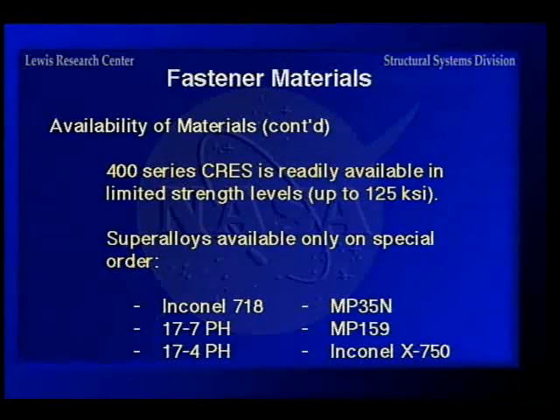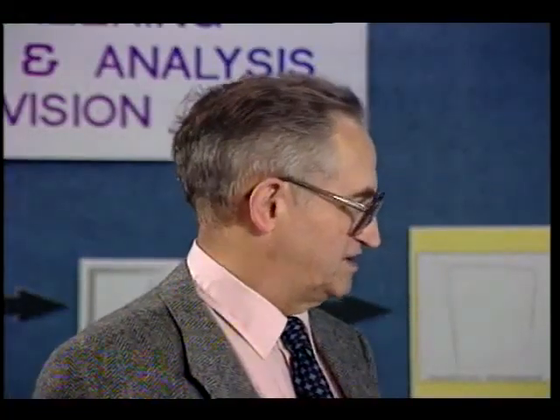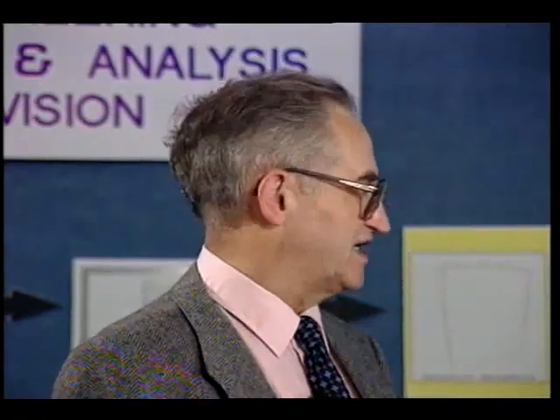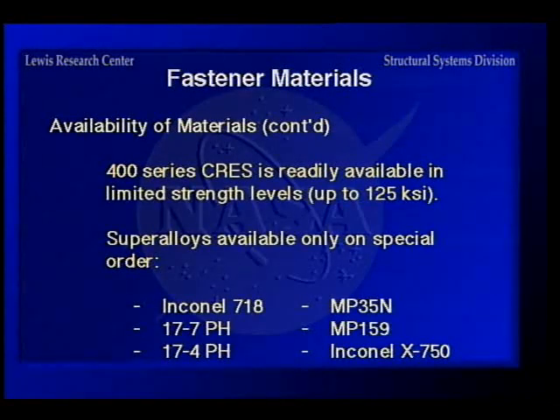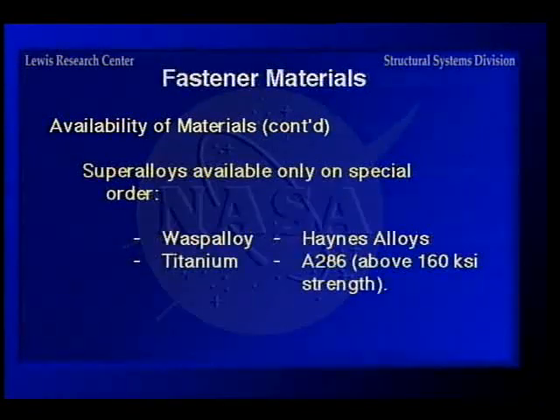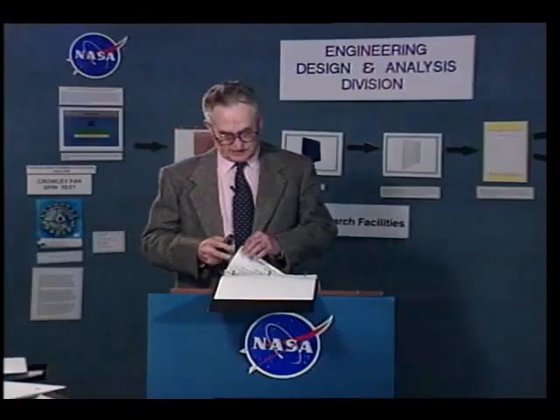Now, the super alloys here, these are the ones that you guys come around looking for when you want something for a particularly stringent environmental set of conditions like high temperature, corrosion, and so on. These are all stainlesses here, well, titanium, of course, is very corrosion resistant also. The MP35N and MP159 are made by SPS. They have the patent on the material, and they are super corrosion resistant and high strength up to about 220 KSI. Inconel X750 is used for high temperature, and the Haynes alloys, and then the A286 above 160 KSI strength is a special, because in order to get it above about 180 KSI, you have to work harden it in addition to heat treating it.